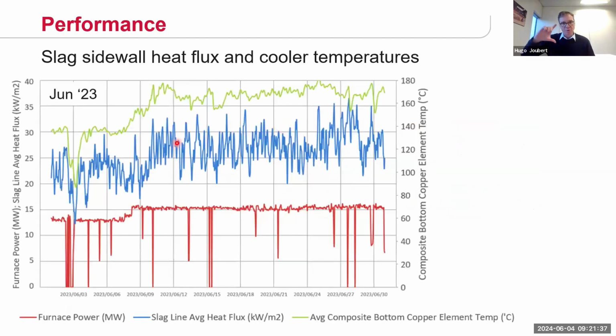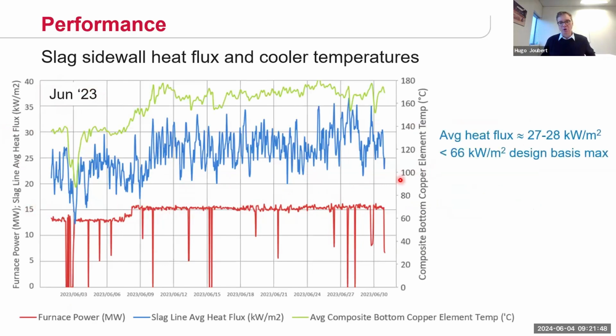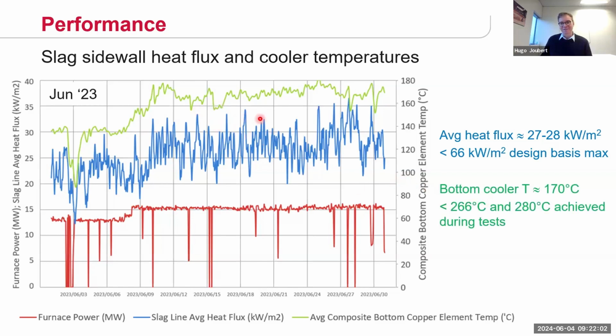So looking at the cycle where we installed the composite coolers, again, this is for June 2023. Again, the red line here indicates the power input into the furnace, just about 15 megawatts. The blue line there indicates the average heat flux around the circumference of the furnace. It's settled at about 27 to 28 kilowatts per square meter, which is lower than the design base maximum. And then the green line indicates the copper temperature that we measure in the bottom copper plate cooler in the bottom row of composite coolers. You can see that settled at about 170 degrees Celsius here, which is much lower than what we achieved